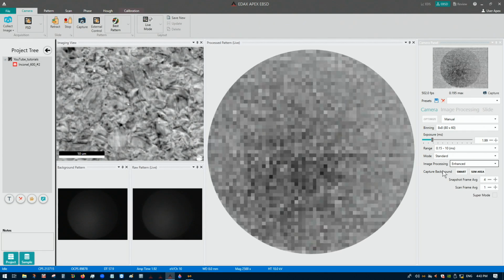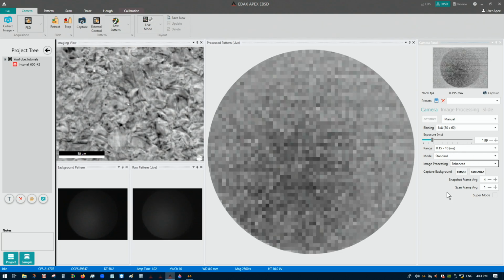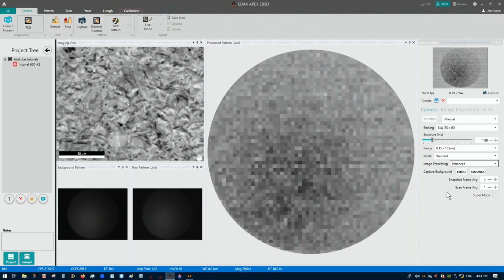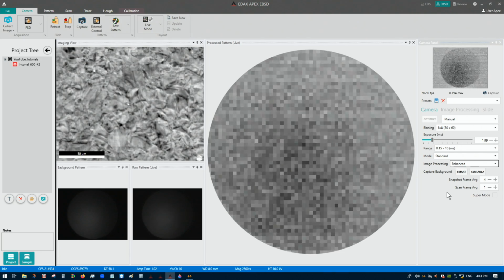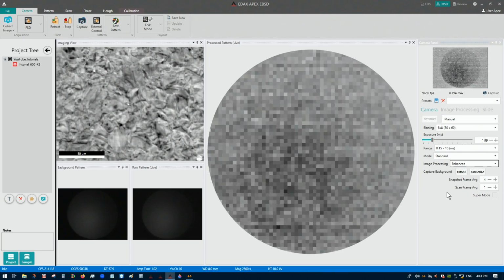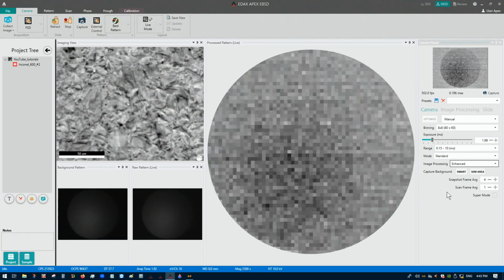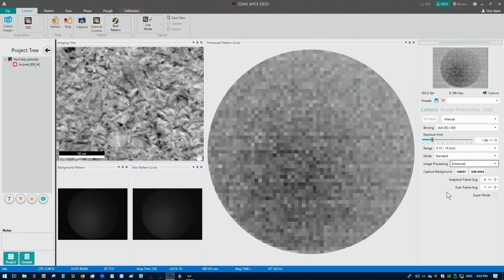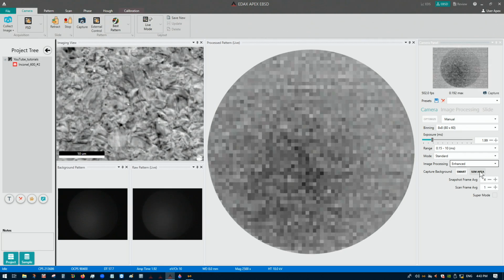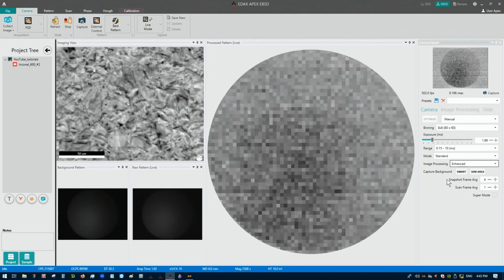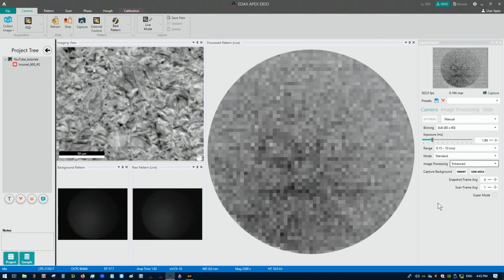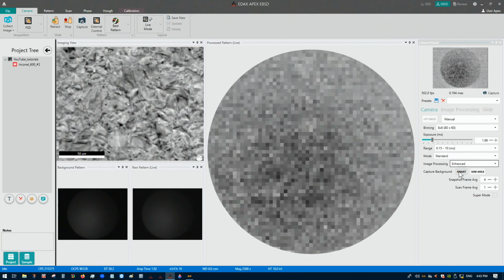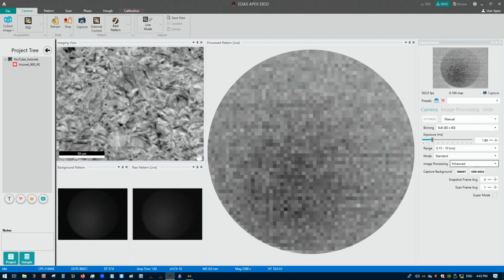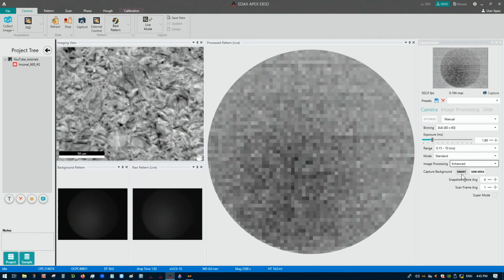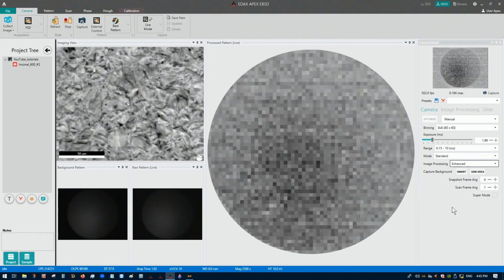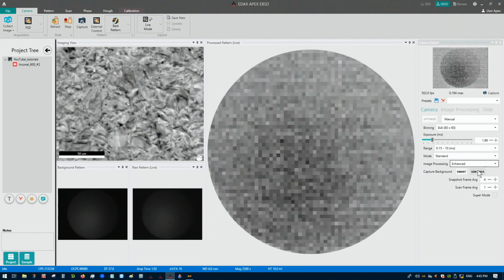And then the background. So this is important, okay? So we need to collect a background. With a polycrystalline sample, it's going to scan over the area and basically collect an averaged pattern, and it's going to call that the background, okay? So if we have a good distribution of grains in our area that we're imaging, we can just do SEM area, okay? If we don't, then we could do SMART, and that will sample a wider area. You have to be careful with SMART, though, because it again goes outside the SEM area, and if this has vacuum or something weird in it, it's going to give you a weird background, okay? So let's go ahead and just do SEM area.